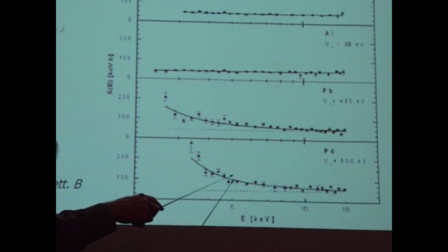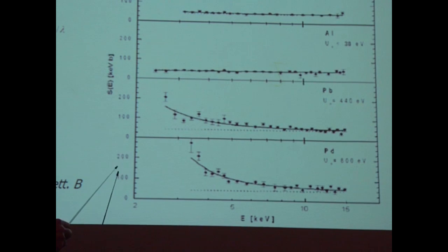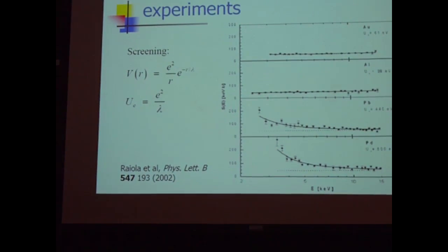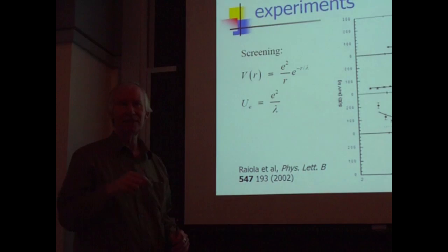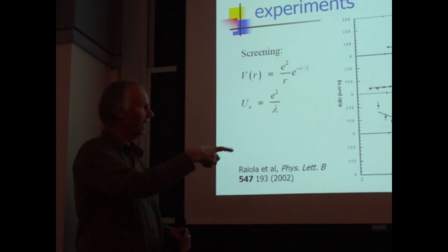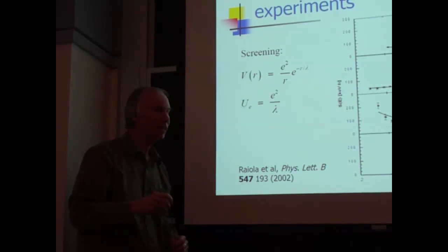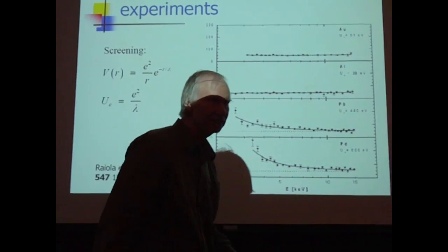In palladium, what you see at low energy is an increase in the astrophysical S factor. In this particular experiment, the screening energy is consistent with 800 electron volts, which means the screening length is ridiculously small. This is interpreted as an experimental observation of large screening.